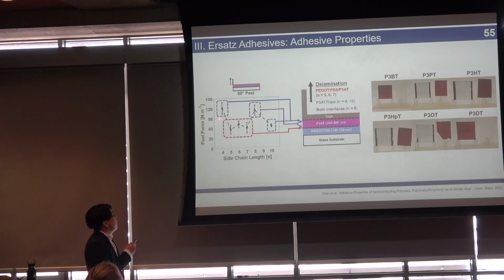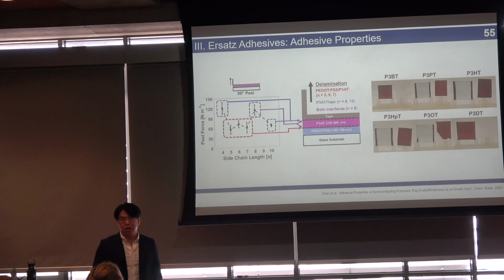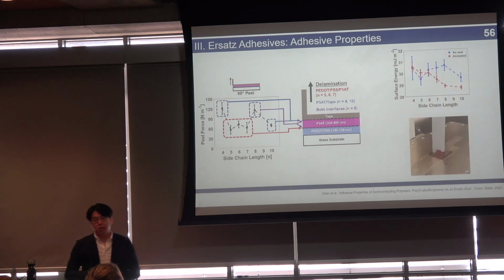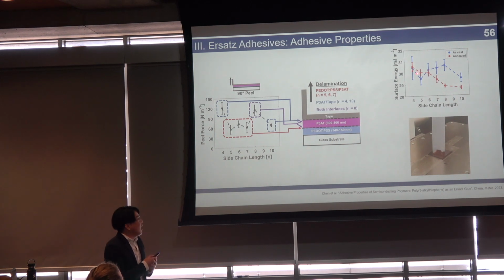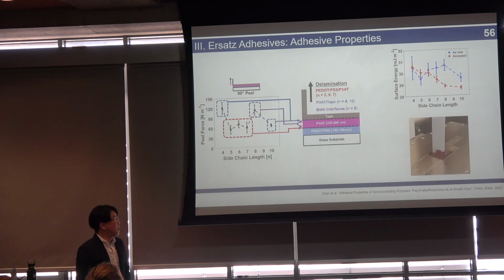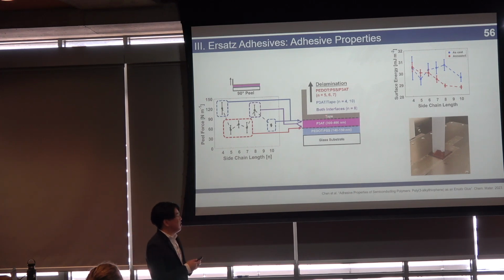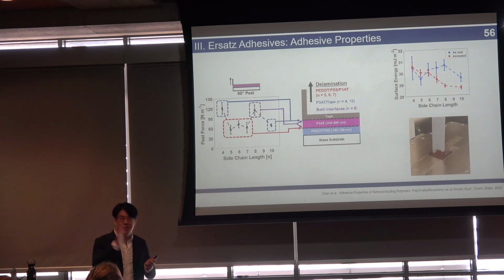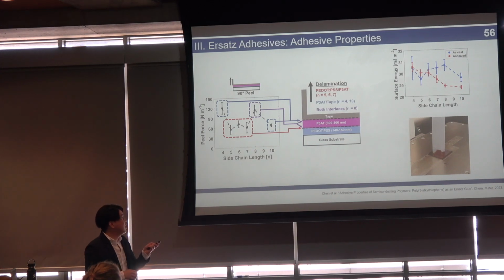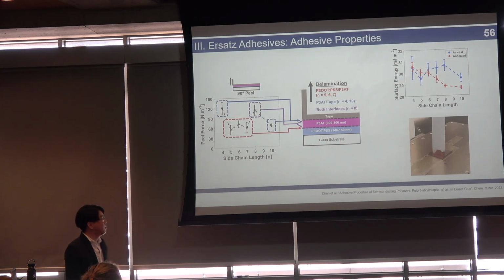So why is this happening, right? You have materials on the opposite ends of the spectrum, and they debond the exact same way, but clearly for different reasons. So what we did was look at the surface energy using contact angle measurements, and we saw that as your side chain increases, your surface energy decreases, which suggests a trade-off between how well your material can adhere to the bottom layer and how well the tape can adhere to the P3AT layer. So P3OT in particular represents a transition where it eventually becomes unfavorable for the tape to stick to your polythiophene layer, and thus you get debonding at two different interfaces. Your material wants to rip off both at the P3AT-tape interface and at the PEDOT:PSS-P3AT interface.